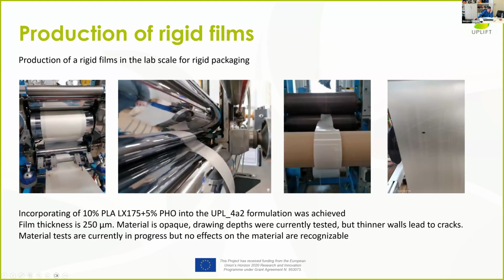We take this material from the flat sheet extrusion that was developed and tried now to produce sheets with a flat sheet extrusion, and you can see here the results. The most part that was spent here was finding the right parameters, because if you have different temperatures on the rollers of the calender, or the draw off speed of the calenders is not good, you have various thicknesses of the films, and sometimes you have problems with the surface, or you also get defects on the surface. So here, finding the right parameters was a challenge, but at least we can say that the compound was successful, and we were able to produce films, flat sheets, with film thicknesses down to 250 micrometers.